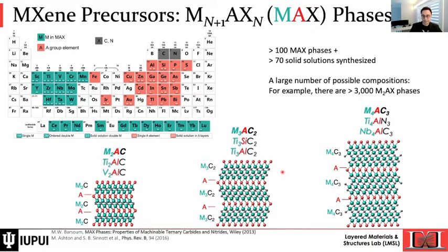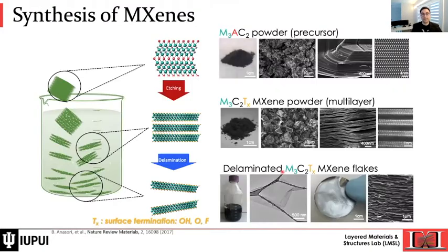When we have these MAX phases, we place them in a selective etchant. Something that started in 2011 and has gone on since then is usually a hydrofluoric-containing acidic solution. The hydrofluoric acid will selectively remove the A layer, which is aluminum here. And so we put in just the powder. You see, it's a gray powder of carbide. We place it into the acid.